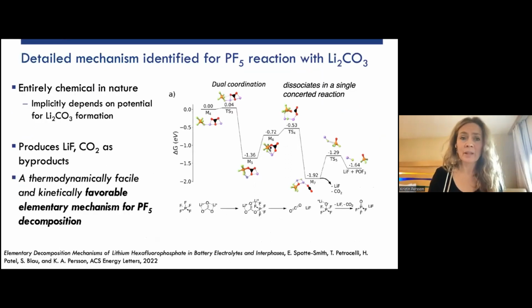So I was very fortunate to work with a graduate student and an undergraduate student that spent an awful lot of time really just moving lithium PF5 and lithium carbonate around, and very careful work showing that if you dually coordinate PF5 with lithium carbonate, they vigorously react. And you can show that it's downhill with a very small amount of barriers forming lithium fluoride, carbon dioxide, and you basically get a continued reaction in that sense. So now we do know how lithium PF6 or PF5 decomposes, so we can add that to the reaction network.